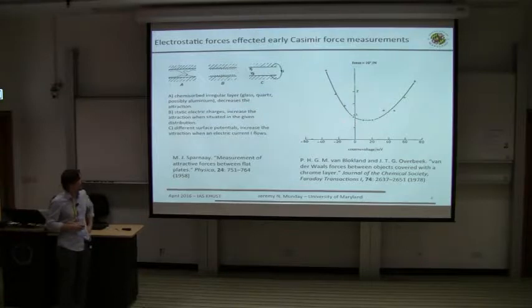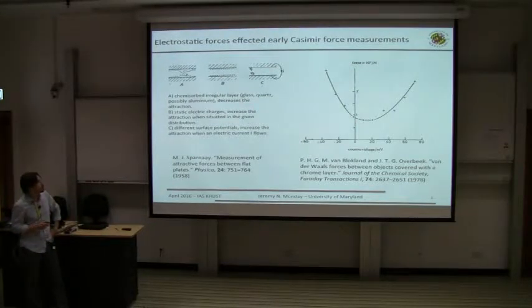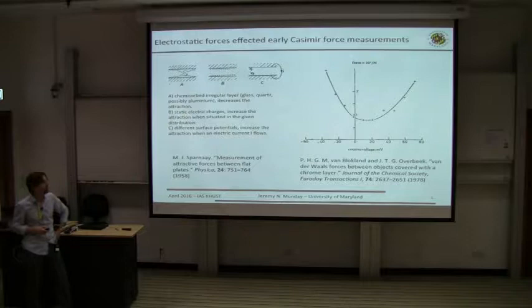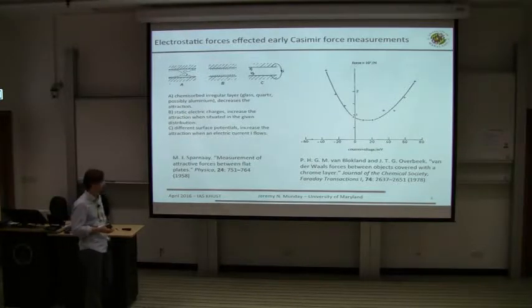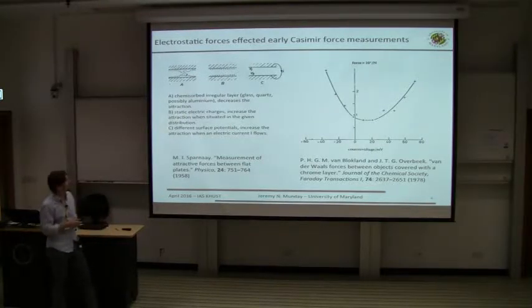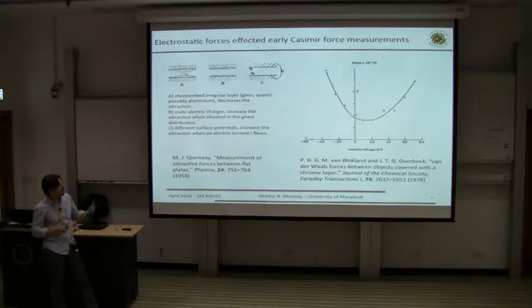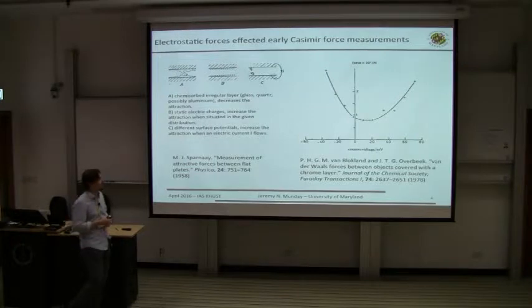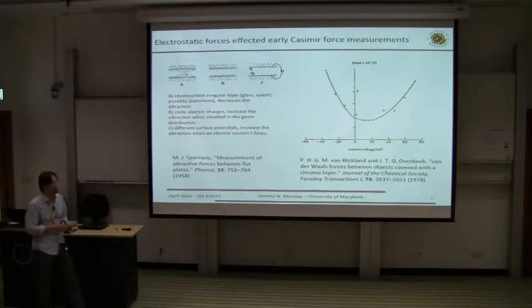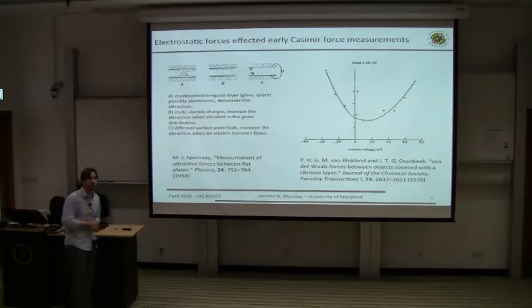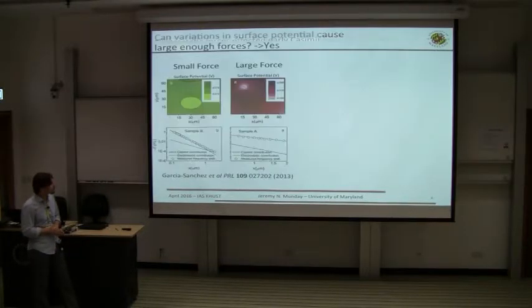In this experiment, Van Blokland and Overbeek were looking at two chrome objects, this time a plate and a sphere rather than two plates. And here they were actually controlling the potential difference between them. The idea is that you could basically tune it so that you'd have zero voltage between them. They still ended up finding something on the order of 10 or 15 millivolts difference between them, even though they're the same material. But this is, again, an electrostatic effect that started playing a role here.